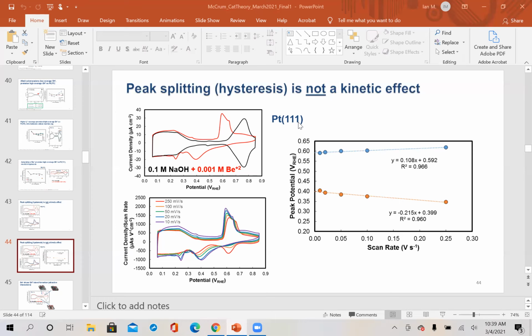I think the difficulty there is we see that hysteresis even before we think we're getting this place exchange. And so it's hard to know, is the hysteresis just in the kinetics of oxygen adsorption, or are we also changing the surface structure by lifting up these platinums? The simple answer is yes, I think it certainly could be related. There's lots of interesting things we could do there, but it's hard to know for sure right now.